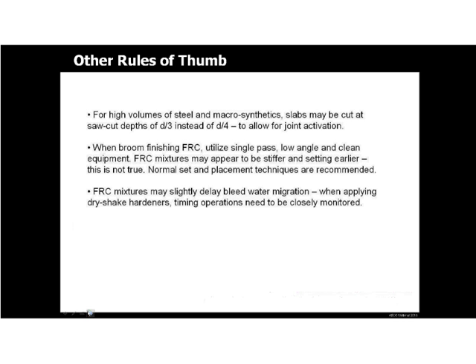Also, when you are broom finishing fiber reinforced concrete, a typical concern that comes up from many contractors is that you see fibers present on the surface. Some of the things to alleviate and not necessarily eliminate is to ensure that you do single pass, low angle, use clean equipment, and watch the timing of your finishing. Fibers in general do not alter the setting times of concrete.